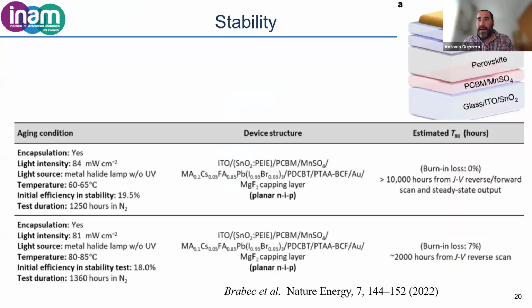Okay, for example, this is one example where the stability of the solar cell has been improved dramatically to more than 10,000 hours for the T80, under illumination and elevated temperature. This work is by Christoph Brabec and colleagues, and in this case by modifying the contacts. So here you see that on top of the conductive oxide there are 1, 2, and 3 layers, and on top of the perovskite there are 1, 2, 3, 4, and 5 layers. Some of the role of these layers is to stop the ions from reaching the contact, which at the end would give degradation of the devices. Okay.